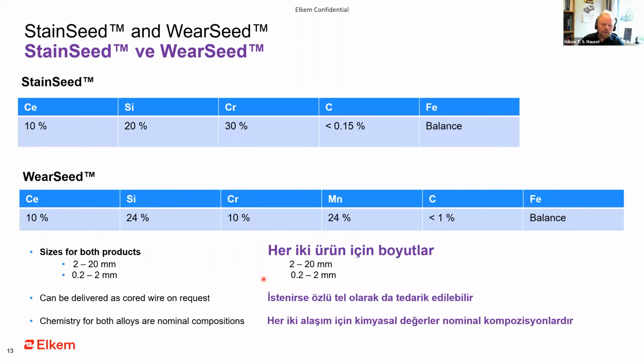So here we have the two alloys. First of all, we have the stain seed, which is meant to be used for stainless steels. The nominal chemistry is about 10% cerium, 20% silicon, 30% chromium, and then less than 0.15% carbon, as most of the stainless steels are very low in carbon. And then iron makes up the balance.